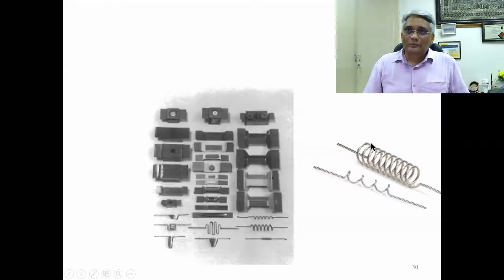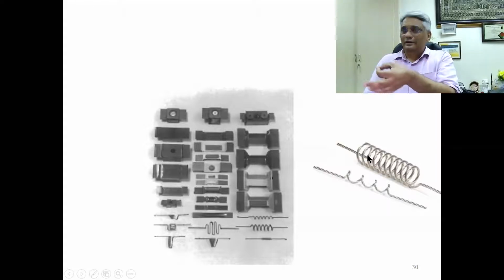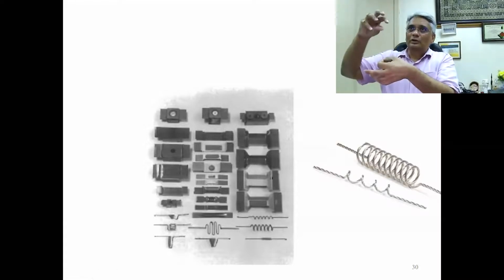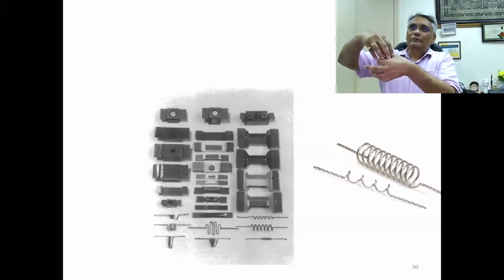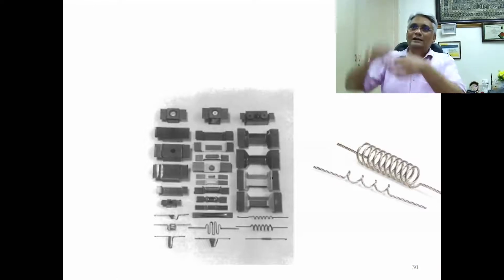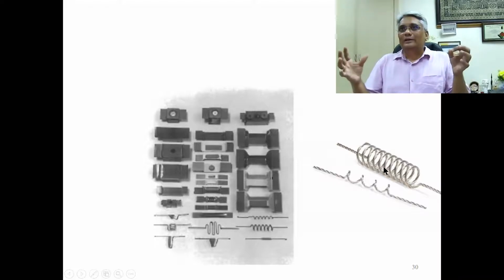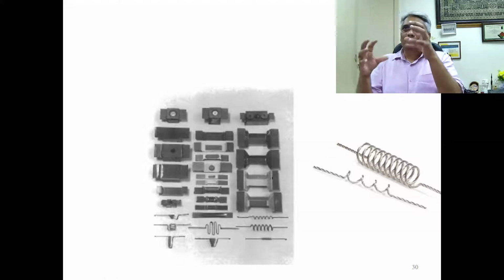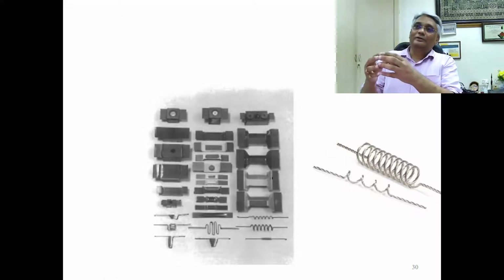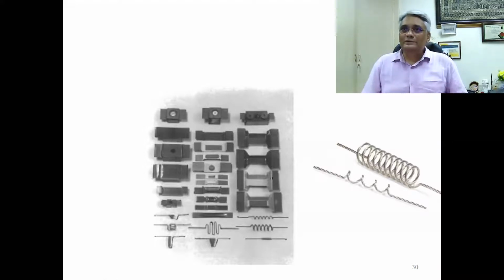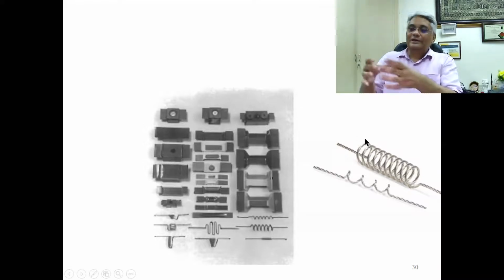But there's a problem here. Now, you can imagine this. Now I have a coil like this, right? I put a charge on top of it, a small lump of metal. So when the metal starts melting, it loses its volume, right? So after a certain stage, the melt can drop down off the heater. That's it. So that means until the point that the radius of the ingot or the metal piece is larger than the radius there, it's held there.